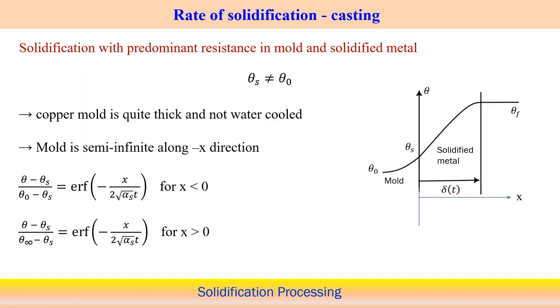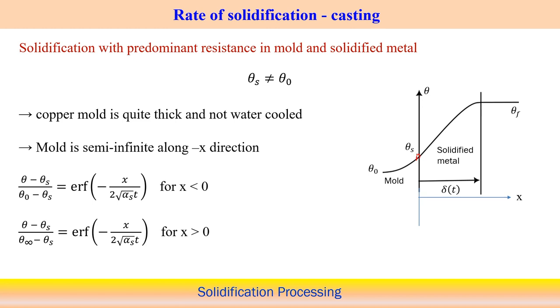Now we can look into the other case also, which is a more realistic problem compared to the previous one, because previously we assumed there is no temperature gradient in the mold metal thickness direction. But in this case, we can assume there is some thermal resistance along the mold wall also. This situation arises when the mold wall is very thick, a copper mold, but at the same time there is no need of using any water cooling system. It means that the heat dissipation through the copper mold is not infinite, or not very high, rather having some finite value. Based on that, there must be some temperature gradient along the mold interface, so there must be some temperature differences.